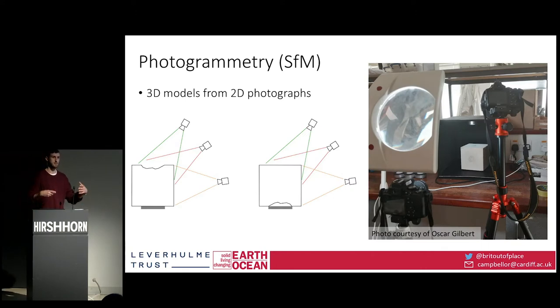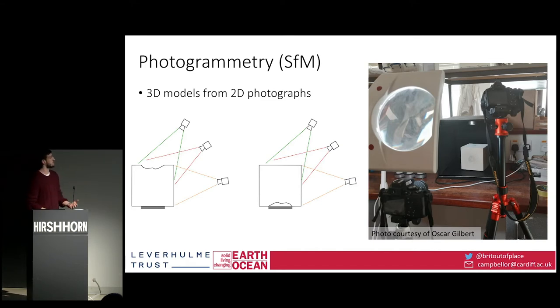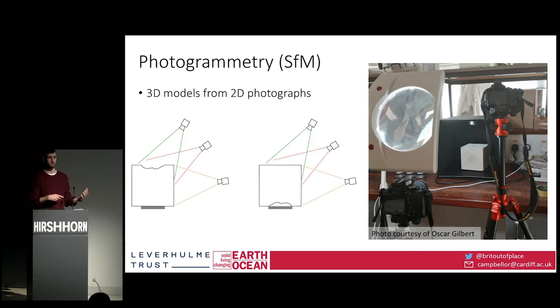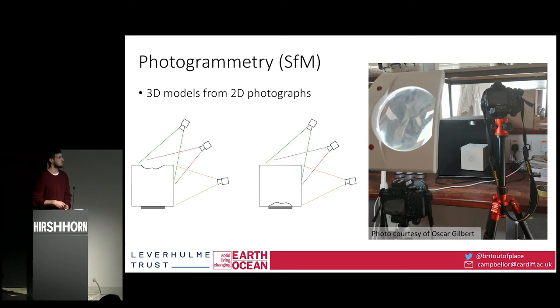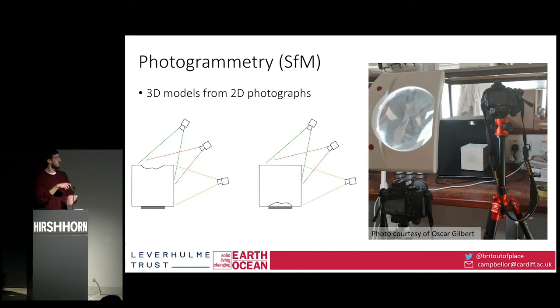From the title of my talk, I'm going to start with macro-scale surface observations and work my way down through the scales of observation, right down to the grains that make up the stone. The first method is photogrammetry — simply put, that's the generation of a 3D model from a series of 2D images. It's an incredibly useful and powerful technique, relatively low cost, and accessible to everyone. What we did is put our block in a homemade light box with some LED lamps and a couple of cameras on tripods, and we rotate the block.